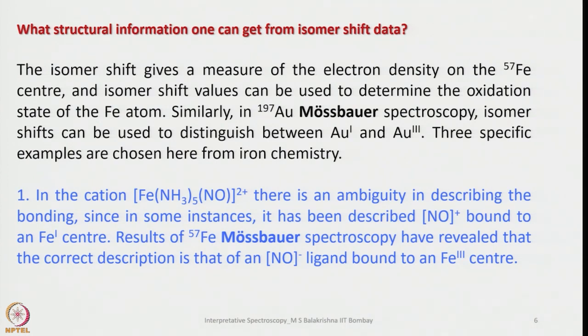Iron 2, on addition of NO, assuming it is NO plus, turns its oxidation state from 2 to 1. Results of 57 iron Mössbauer spectroscopy have revealed that the correct description of NO is not NO plus, in fact, NO minus ligand bound to an Fe3 center.